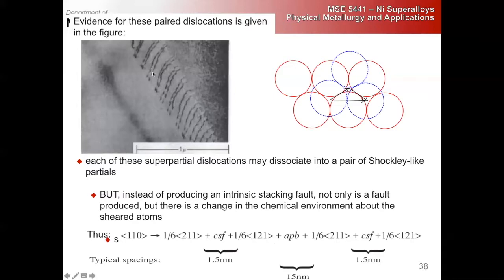And here we can see these are the Shockley partials, right? This is the gamma prime interface. These are wrapped around. The geometry is difficult to get your head around when you first start thinking about these things. But we have loops of partials in the gamma that wrap around the gamma prime particles. Okay, so this explains why gamma prime is such a good strengthener, but it still doesn't explain the anomalous hardening, right?